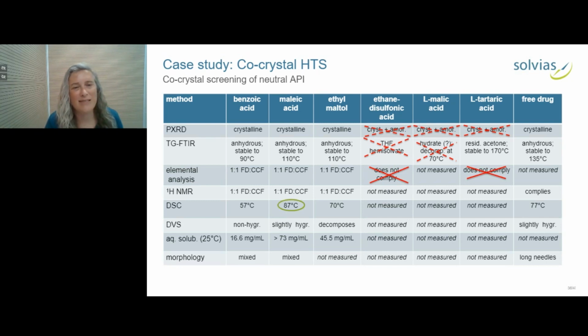And we can see, for instance, maleic acid had a melting point that was 10 degrees higher than that of the free drug. And looking at the dynamic vapor sorption, the free drug and the maleic acid co-crystal were slightly hygroscopic, but the benzoic acid one was non-hygroscopic. The ethyl maltol decomposed, so that eliminated that co-crystal former. All 3 of them had suitable solubility.